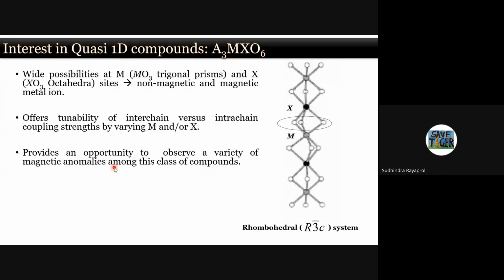Talking about this quasi one-dimensional compound, we have a situation where we have two transition metal ions. It can be magnetic, it can be non-magnetic also, but one of them has to be magnetic. And when you place them alternately along the c-axis, there is one phase. When you have octahedral and tetrahedral positions which are alternately shared, you have magnetic and non-magnetic ions alternately placed. So you have oxygen which is shared between both these transition metal ions, which forms the common surface. But you can see the interaction is mainly along this particular chain, so that is why it is called quasi one-dimensional.